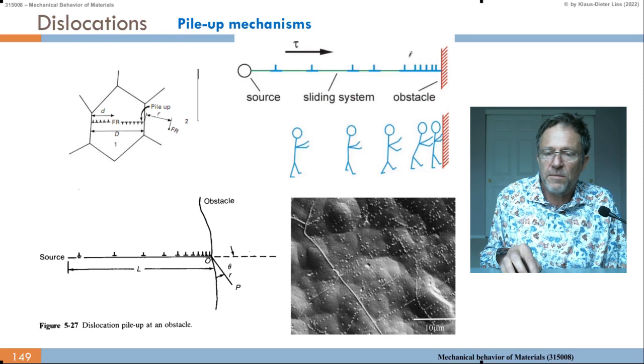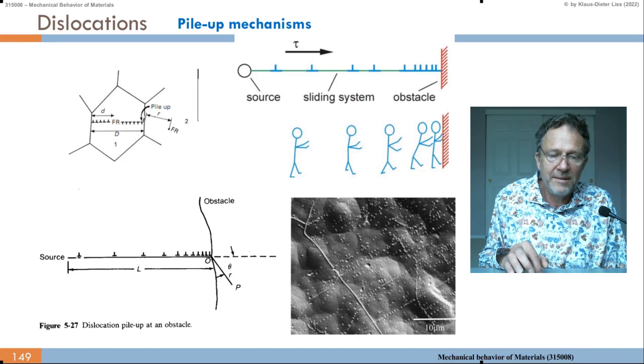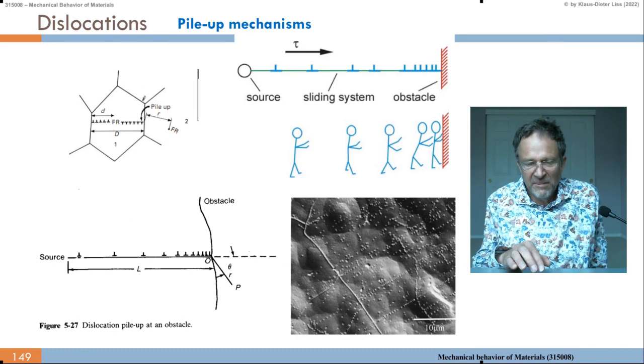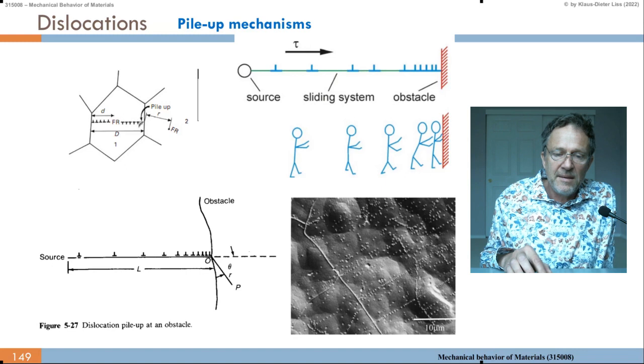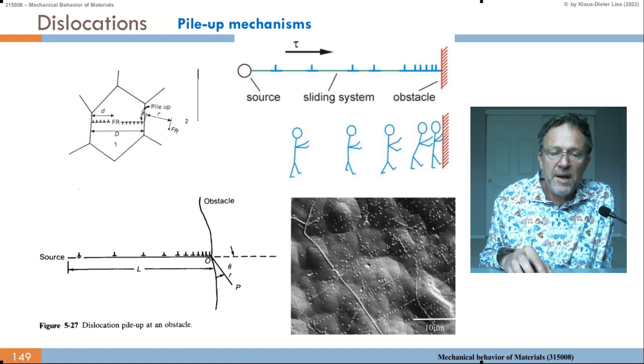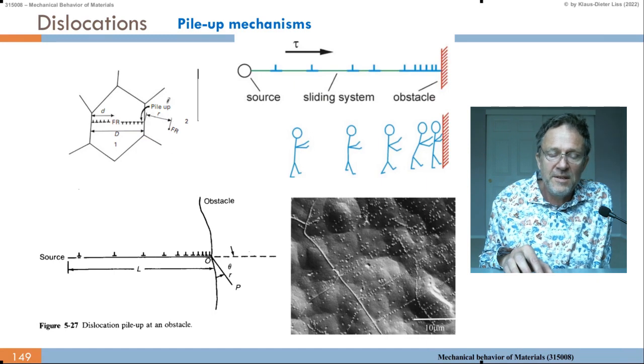Then the next one comes, the third one, the fourth one, fifth one, sixth one. Then here we have others. They are like airplanes flying into the airport, and then they all come to the terminal here. So they line up. Now, this is the obstacle. The obstacle in a grain is typically the grain boundary, as shown here. And these dislocations, of course, push on the grain boundary. They push so hard on the grain boundary until they can go through or introduce a dislocation in the neighbor grain.